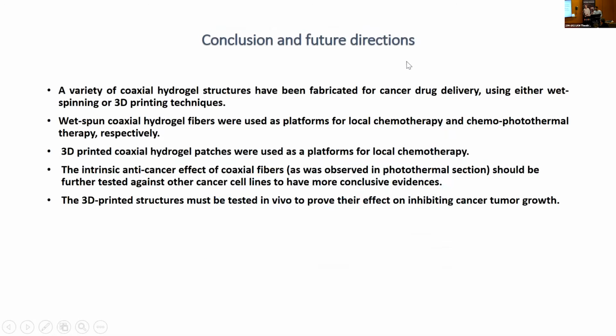So what we concluded was that this specific chemistry that we used, along with this coaxial design that we had in mind, actually worked, whether you make them with wet spinning technique or with more advanced 3D printing technologies. And we use them both for local chemotherapy and chemophotothermal therapy. As I mentioned, we use the 3D printing to make these implantable patches. What's left to be done is more in vivo studies, especially on the 3D printed patches, as well as some in vivo studies on intrinsic and anti-cancer properties of these chemistries that we've chosen.